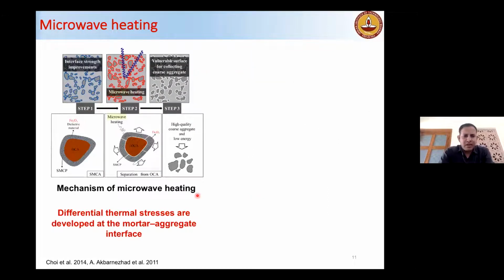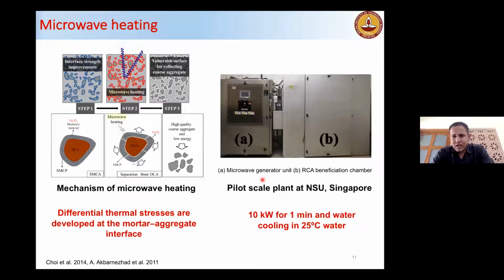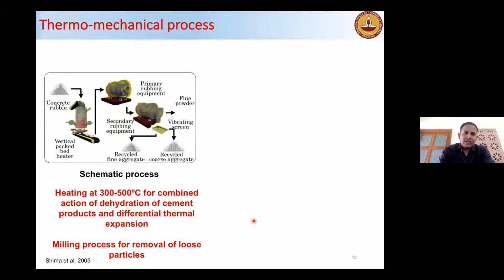Next is the microwave heating, where heating is provided through microwaves, and this basically acts on the ITZs. So basically, you have a different dielectric constant of the mortar and the aggregate. So differential thermal stresses are developed at the interface of mortar and aggregates, and then it is delaminated, and you get clean aggregates. So there is a pilot scale plant in Singapore, where they have used 10 kilowatt for 1 minute, and then after the microwave treatment, they suddenly put the aggregates into the water for thermal shock, and then it is recycled.